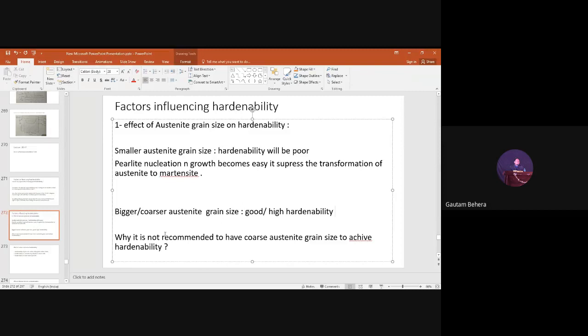Then the next question: why is it not recommended to have a coarser austenite grain size to achieve good hardenability? So what conclusion did you get? The conclusion is: if we want high hardenability characteristics in the steel, then we have to go to a high temperature, right? Because if you go to a high temperature, we will have a coarser austenite grain, and then transformation of austenite to martensite will be easy, because the austenite to pearlite transformation is suppressed due to the coarser austenite grain size, right?